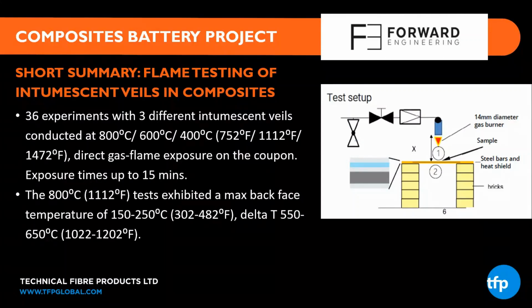So let's get into the results of the project. The first stage of the project involved 36 experiments. Three different grades of Tecnofire intumescent veil were incorporated into composite laminates before manufacture. The post-cured laminates were then exposed to 800 degrees centigrade (1470 degrees Fahrenheit), 600 degrees centigrade (1100 degrees Fahrenheit), or 400 degrees centigrade (750 degrees Fahrenheit), via direct gas flame exposure for up to 15 minutes, and the back face temperature measured.